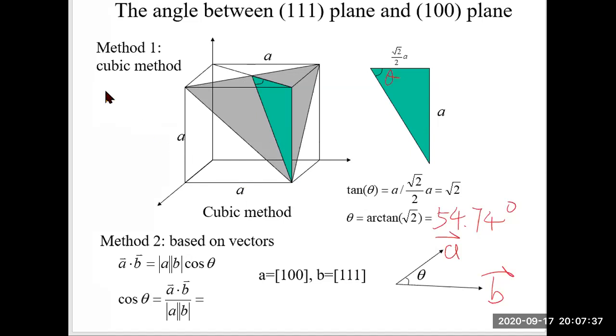Then A dot B is equal to what? A dot B is equal to 1 times 1 plus 0 times 1 plus 0 times 1, so it's simply equal to 1. So cosine theta is equal to 1 divided by what? The length of A is 1. The length of B is the square root of 3. So theta should be equal to arc cosine of 1 over square root of 3.